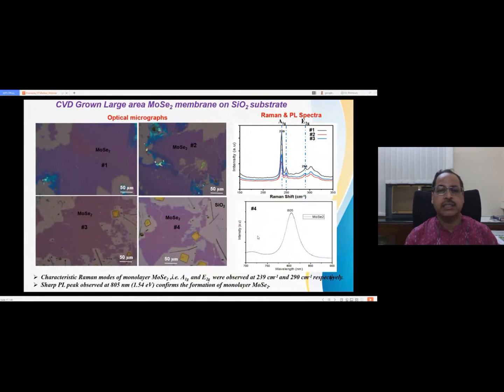And before this COVID pandemic, we were able to grow large area molybdenum diselenide by one of our research students and project staff, who may also be attending this seminar. This is the CVD grown large area MoSe2 membrane on the SiO2 substrate. This is the optical micrograph picture. We grow flakes of around 400 to 500 micrometers. So our aim is wafer scale growth of these 2D materials.